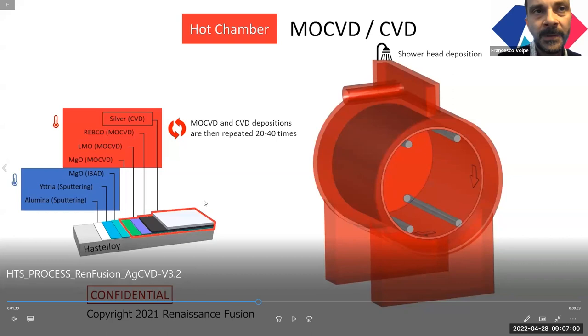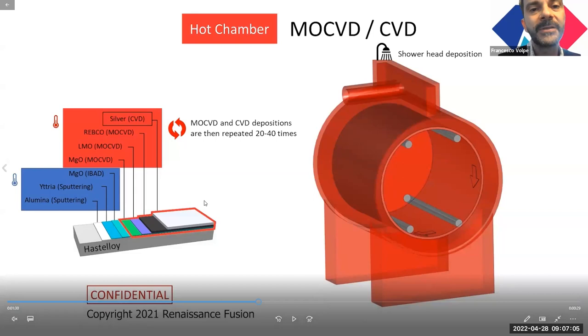So typically silver in these tapes is deposited by sputtering. But the novelty here is that by using MOCVD, we get a textured, epitaxial, well-behaved, good crystal, basically, that we use as the basis for the magnesium oxide for the following sequence. And that prevents the delamination issue that, Thomas, you are correctly pointing out.